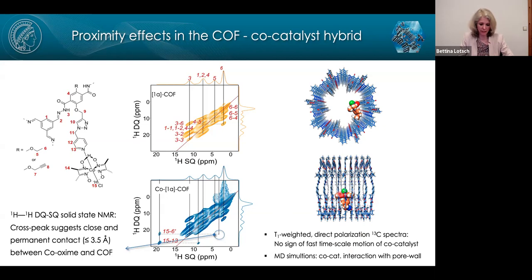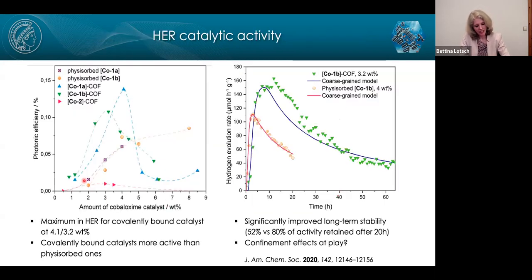And so what does that mean for catalysis? So this is shown here, where we compare now a physisorbed cobaloxime catalyst with the chemisorbed catalysts. And you see that the behavior as a function of cobaloxime content is quite different. So for the physisorbed systems, we see this saturation type behavior, but we see that there is a maximum in catalytic activity, in hydrogen evolution activity for the chemisorbed system. So basically that tells us that there's an optimum, a sweet spot of catalyst loading. And if we go higher, then there's pore clogging, and too low obviously also reduces the activity, which makes sense. What we also see, and that is quite interesting, is that the activities can be higher for the covalently bonded system.